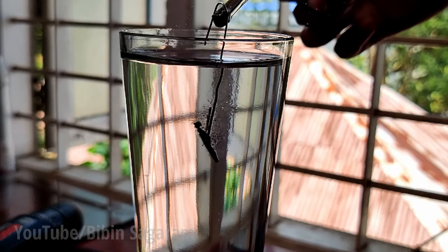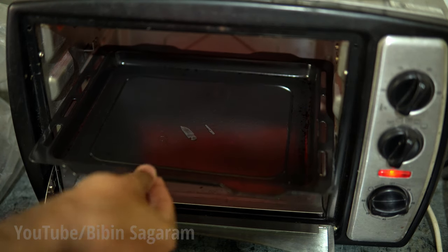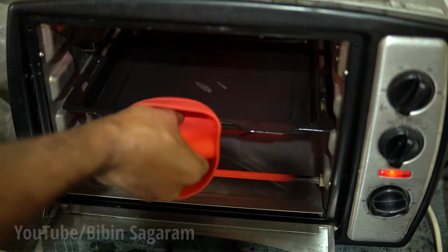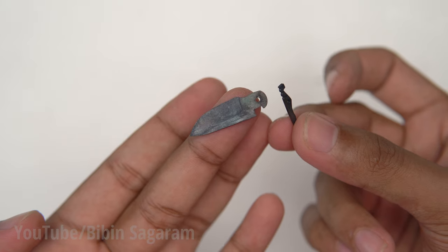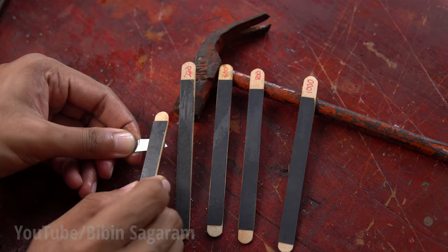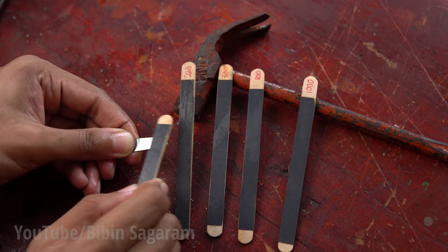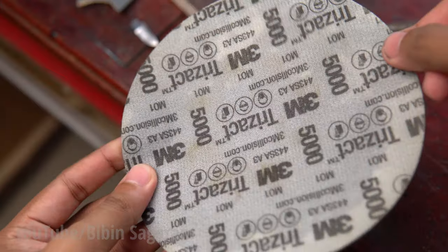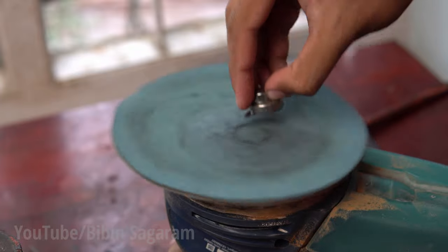Since the part is too brittle after quenching they have to be tempered. They are kept in an oven for 200 degrees celsius. After two hours the parts are taken from the oven and sanded progressively through different grits starting from 220 to 2000 grit and polished using a 5000 grit sandpaper.